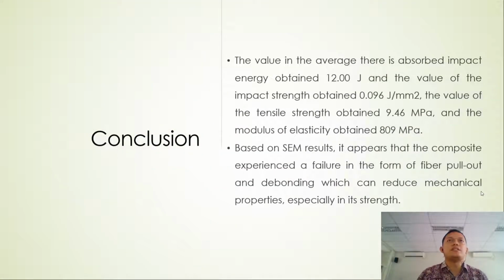So the conclusion in this research: the average absorbed impact energy obtained is 12 joule, and the impact strength obtained is 0.096. The tensile strength is 9.46 MPa, and the modulus of elasticity obtained is 809 MPa. And the SEM characterization shows failure in the form of fiber pull out and debonding.